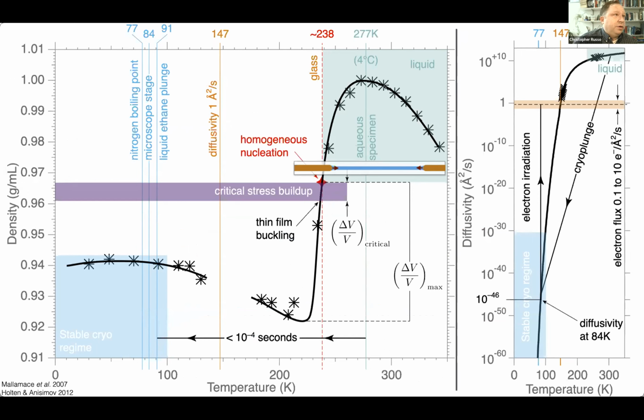So you start out with your liquid water at 4 degrees C, and then as you cool it down during cryoplunging specimen preparation, it gets colder and colder, and eventually you reach the homogeneous nucleation point, which is starred here. So this is the point at which the water actually becomes solid and starts to build up stress. Up until this point, there is no stress built up because it's still a liquid. So it cannot withstand any normal force. It just gets smaller. But here is where you start to build up stress. And then the stress builds up enough that it actually exceeds this critical threshold and buckles.